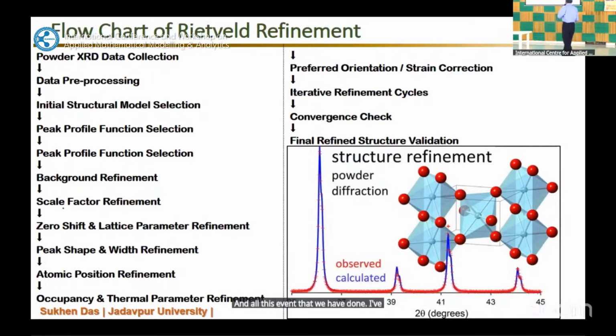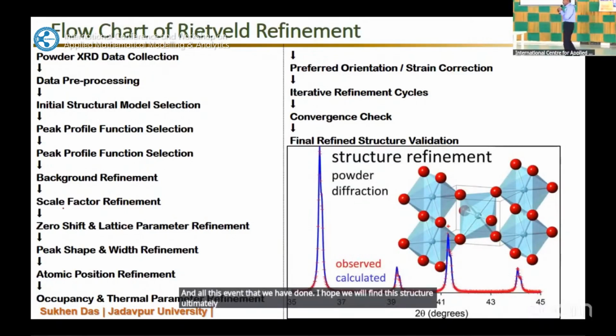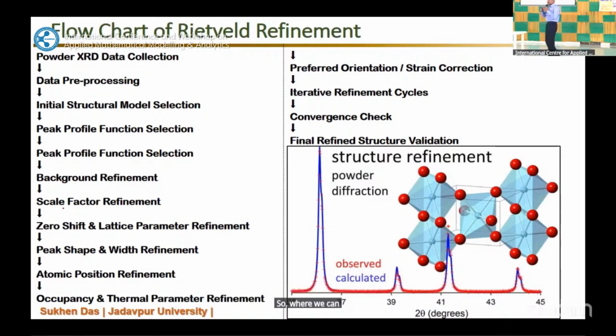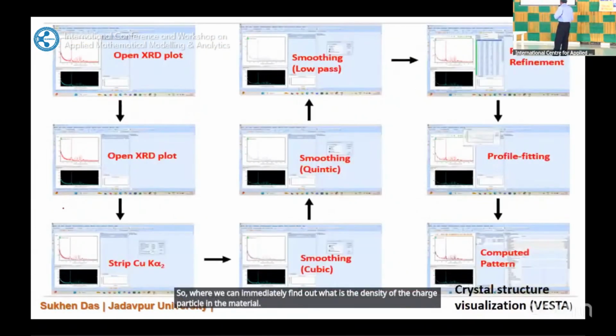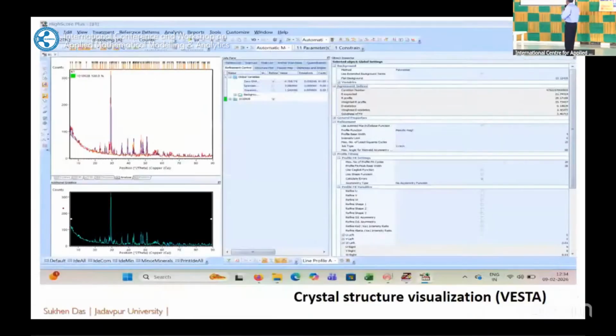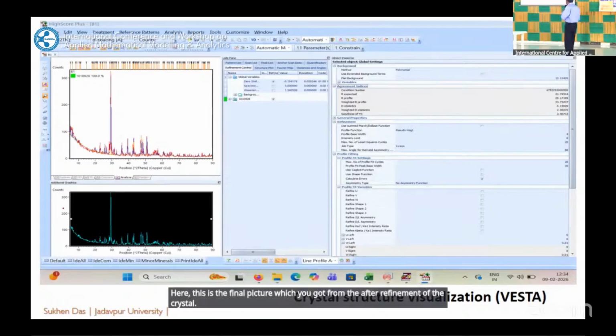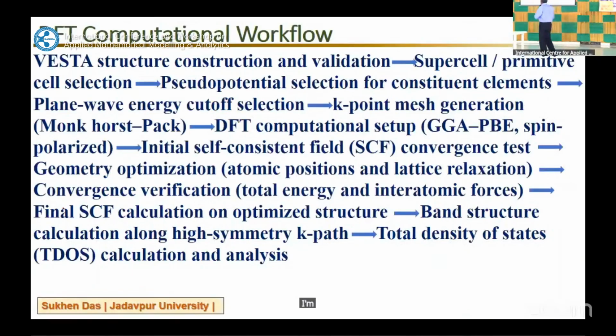And when we refine this structure, ultimately we will get the actual structure of the material, and that structure will be compared with the structure which we will get, and from there we will get a crystal structure like this, from where we can easily find out what is the density of the charged particle in the material. So this is the final picture which you get after refinement of the crystal. And from there we will start the DFT computation. That means the density functional.